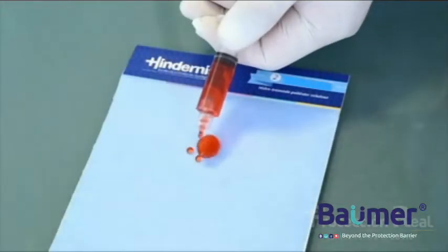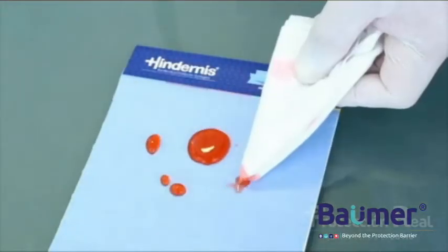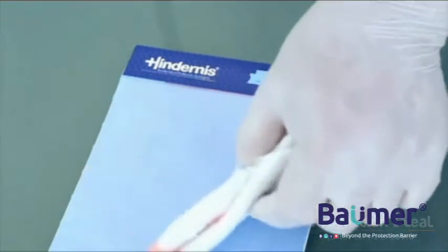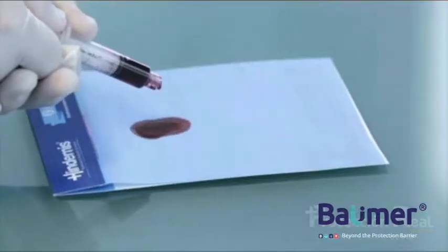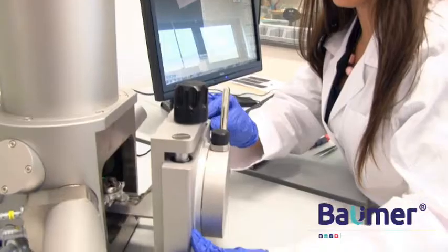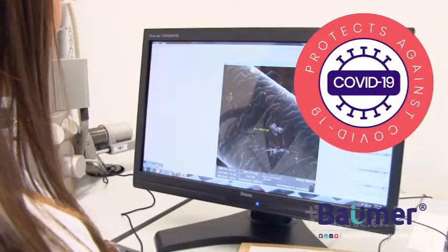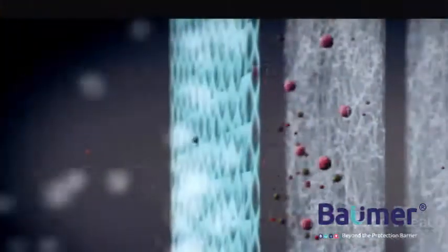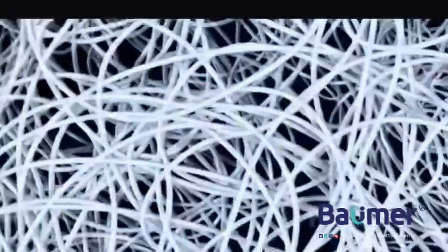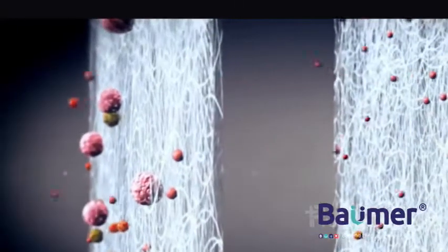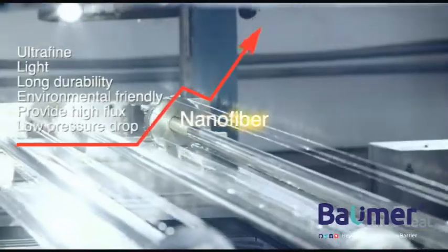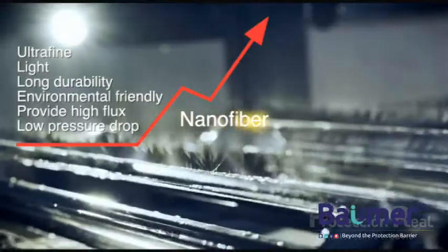This material provides the fabric not only with high breathability, hydrophobicity and oleophobicity, but also the durability of effective barrier parameters even after 120 hours of use. Our fabric composes a layer of modified polypropylene nanofibers, which contains two fractions of nanofibers with different diameters, because this structure achieves a more advantageous combination of breathability and hydrostatic resistance.